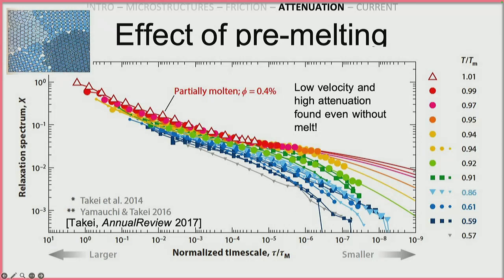And here's where that black data from the previous slide was. Down here, it's a very low homologous temperature. They systematically increased it to approach melting, and they saw this gradual increase in the attenuation. So what's that all about? The same thing I just said about the superhighway of melt creating fast diffusion also happens before melting.